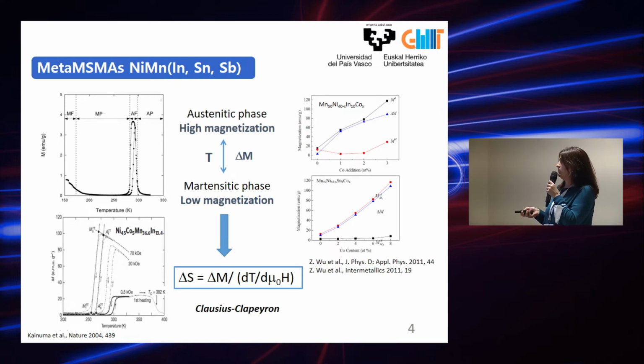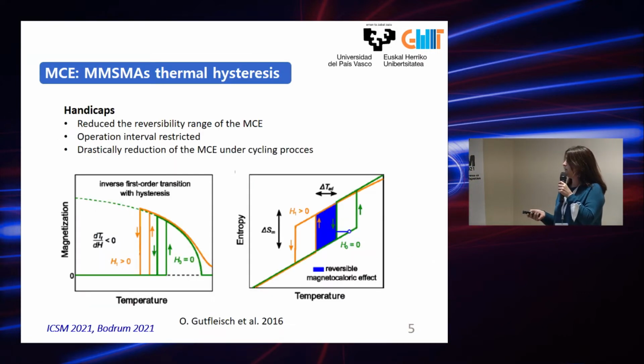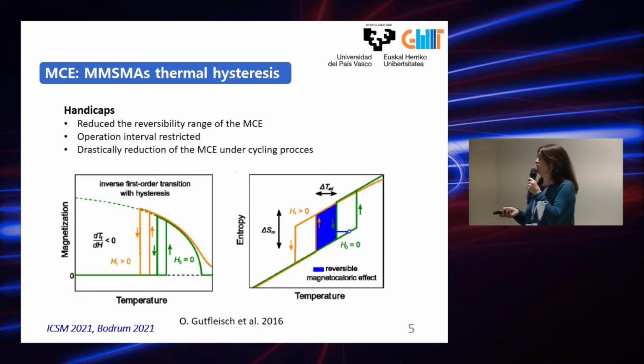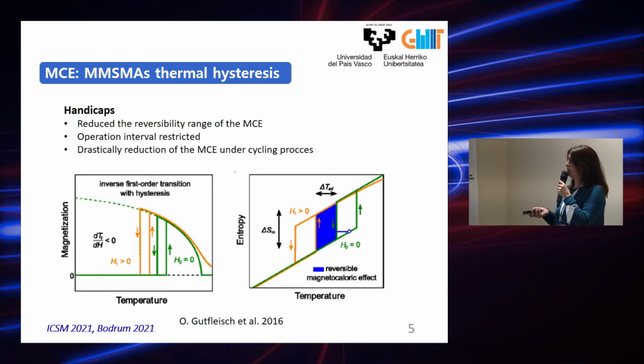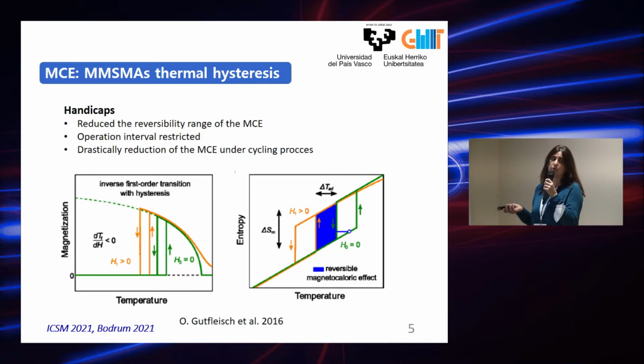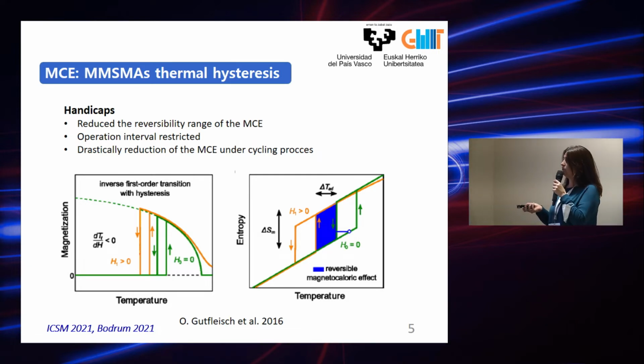A lot of efforts have been made in order to improve these parameters with different dopings and different compositions. But still, there are some problems in these materials that are inherent to the first order structural transformation that they present, and this problem is related to the thermal hysteresis associated with this first order. So this means that we cannot have a reversible magnetocaloric effect, and it also restricts the operation interval, and as we want these materials to be cycled for refrigeration, we lose this magnetocaloric effect.